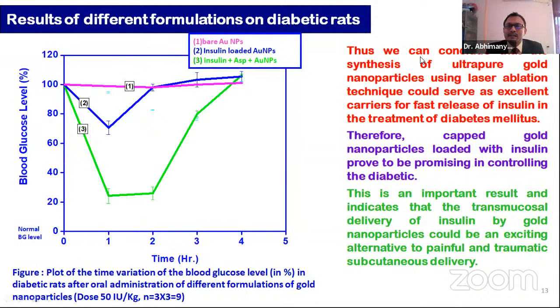Thus we can conclude that the synthesis of ultra-pure nanoparticles using the laser ablation technique could serve as an excellent carrier for the fast release of insulin in the treatment of diabetes mellitus. Therefore, capped gold nanoparticle loaded with insulin proved to be promising in controlling diabetes.